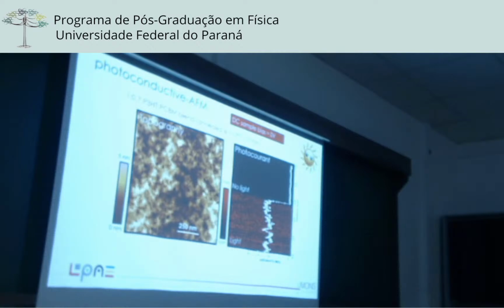process. Once again, we have no light and we have light here on the sample, compared to the topography. There is no modification of the topography, and we have this situation. So the PC-AFM is really working as an OPD. And now we can start to measure different OPD systems, and also some perovskite, hybrid systems, because we have the sample and we can start to measure.